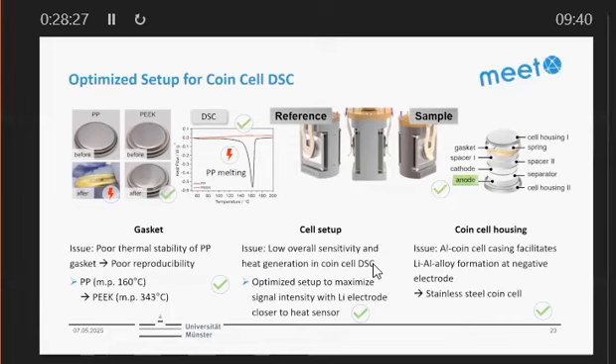Guess what is used in all DSC measurements in literature for sealing? It's polypropylene. So we changed this to a different polymer. And this polymer melts at 340 degrees C. And this helps us to get reproducible safety data for the DSC.